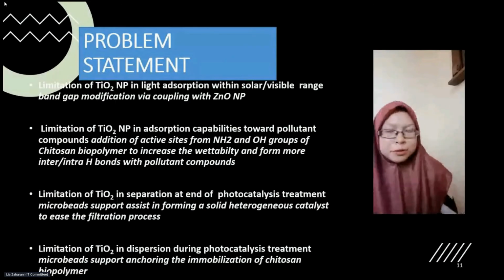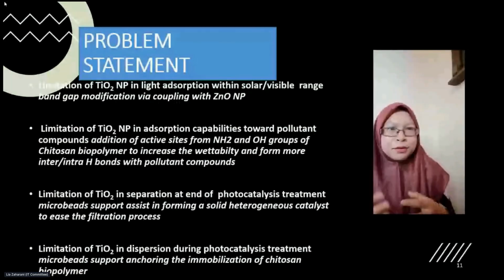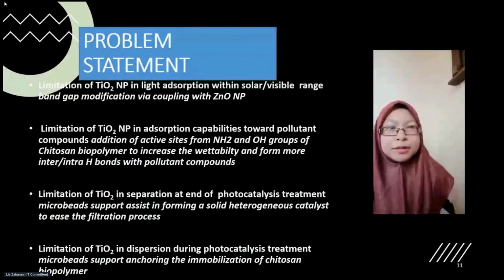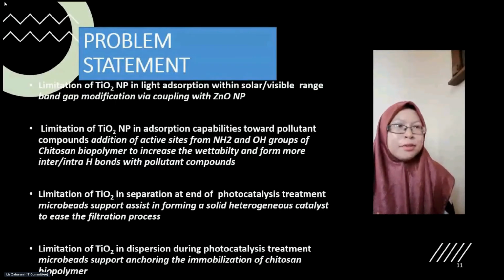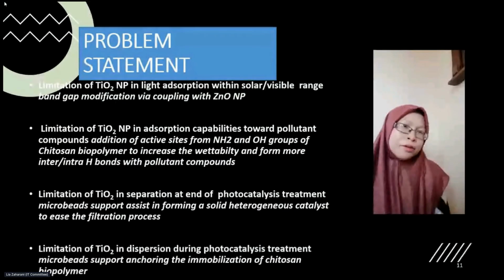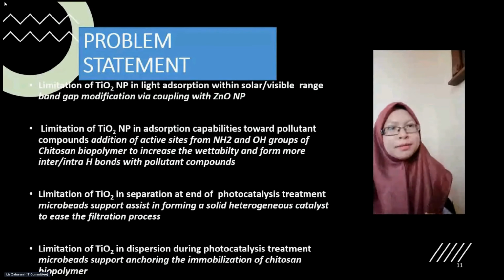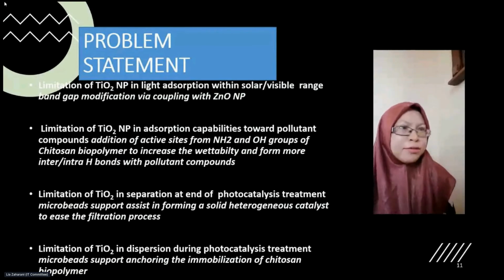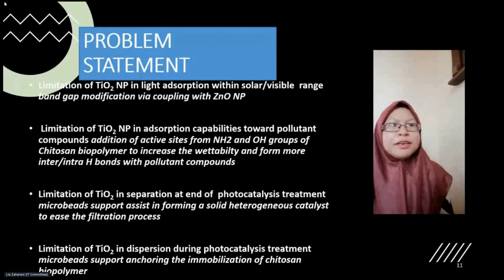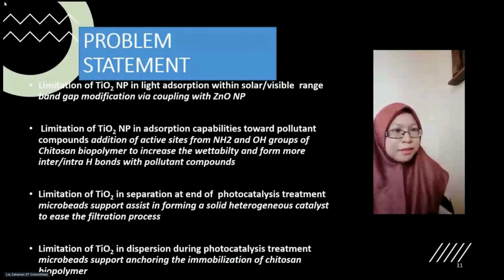It is well known that the application of photocatalysts, such as the metal oxides titanium oxide and zinc oxide, is limited by the fact that UV activation is required. The band gap energy is about 3.2 eV, and this implies that less than 5% of the solar spectrum has sufficient energy to activate the photocatalyst, and by the fast recombination rates of the electron-hole pairs generated.